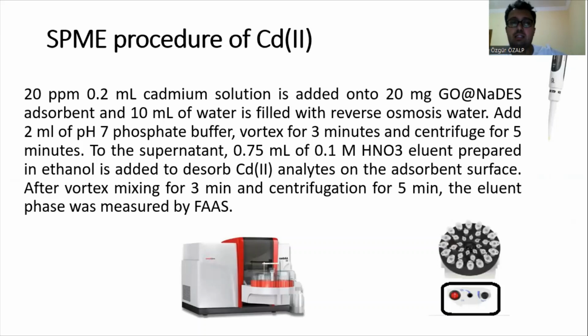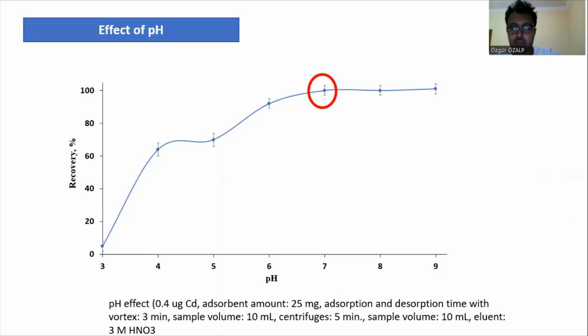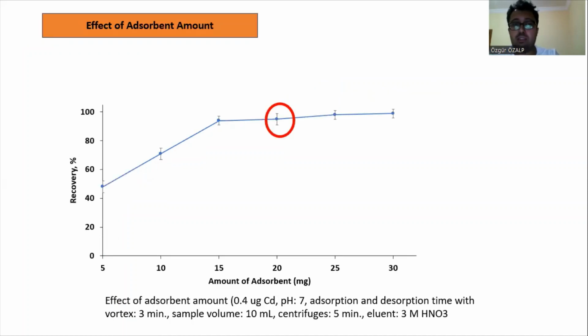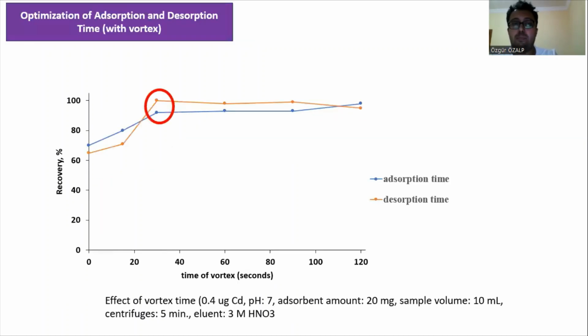Optimum experimental design. You can see the procedure: cadmium and pH 7 buffer. After mixing, we add the nanocomposite, and after mixing and centrifuging, the upper phase is removed and we add nitric acid, then repeat the same procedure of stirring and centrifuging. We analyze this with atomic absorption spectrometry. The optimum pH is 7. For adsorbent amount, we select 20 milligrams, and the adsorption and desorption vortex time is 30 seconds for both.